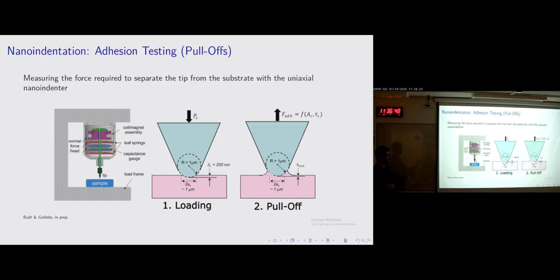And basically I do a loading and then an unloading on the sample. The first stage is loading. I load the tip. This is the nano indenter tip here in light blue. I show here a spherical tip, or a sphericonical. It's a cone ending with a sphere. And it indents into this sample right here. We reach some indentation depth and there's some contact area, and we know what the contact area is.